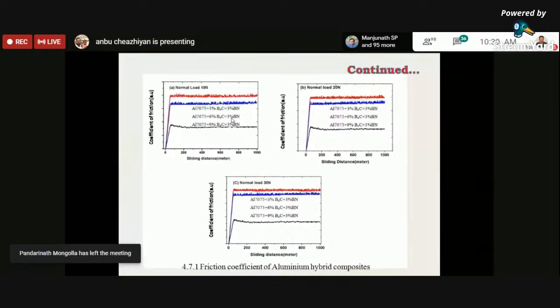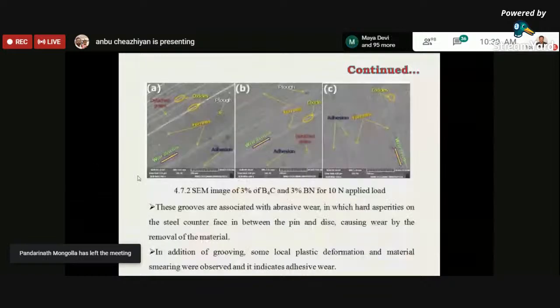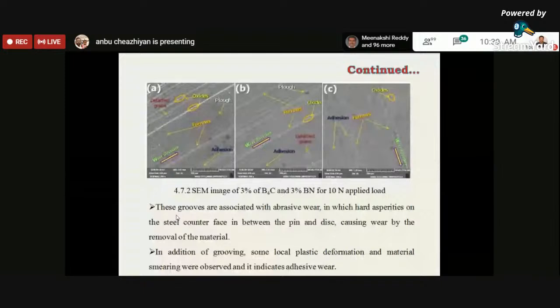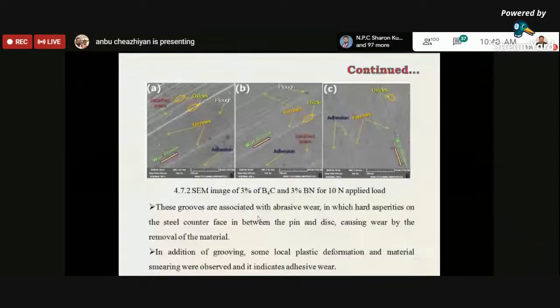Next, we'll go for worn surface morphology. So here, the worn surface of all the specimens under variable load were covered with grooves parallel to the sliding direction and some plastic deformation. These grooves are associated with abrasive wear, in which hard asperities on the steel counterface, in between the pin and disc, cause wear by the removal of material. It is also observed that due to the presence of hard reinforcement, the presence of adhesive wear is less, and hence the total depth of deformation is smaller in hybrid composites.